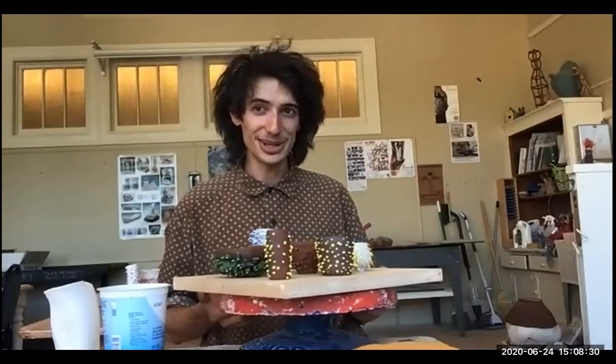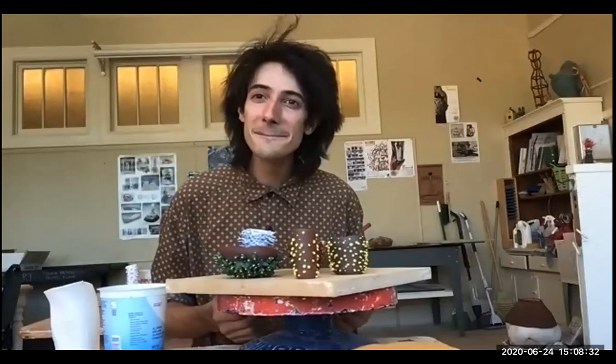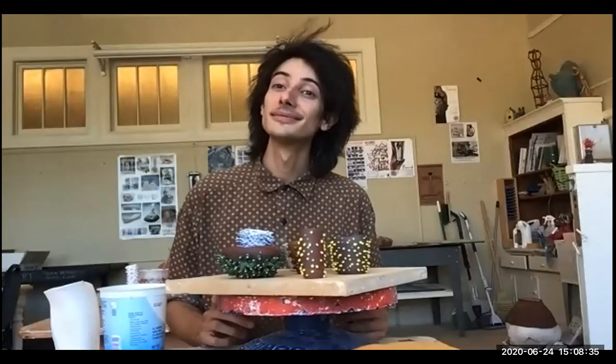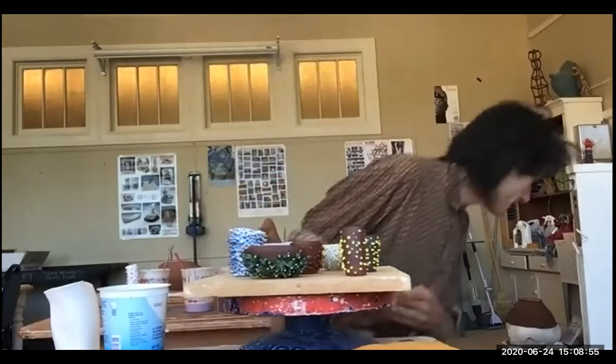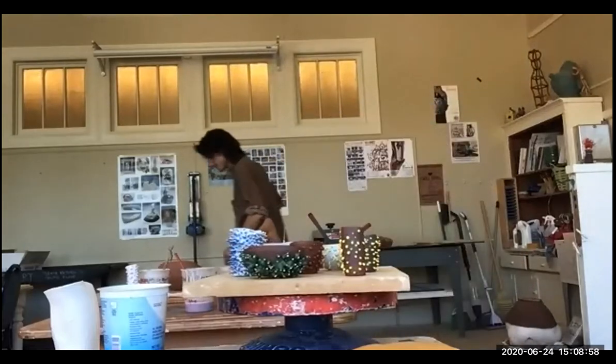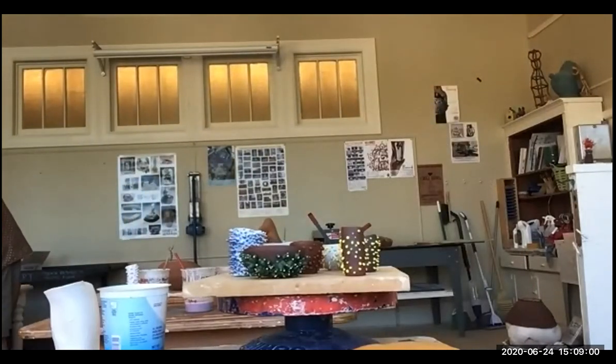No, I don't want recipes because I want to experiment myself, but what I see in your piece is that when I use glaze with silicon carbide, I don't have any control on where the bubbles are formed. Your piece looks like you just put a blob and inflated, but it's not. So you put more clay in the glaze and then add silicon carbide? Essentially, yes.